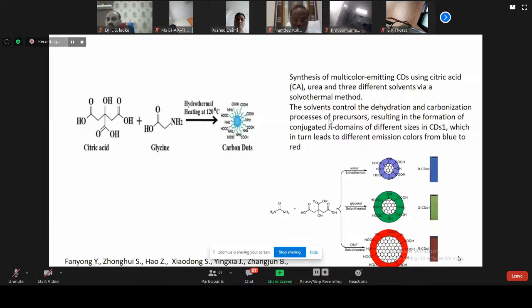Okay? So on the other side, we'll see a typical example of a multicolor emitting carbon nanodot using citric acid, urea, and 3 different solvents. When I do my synthesis in different solvents, I'm going to have a particular color being emitted. When you look at the reaction, urea and citric acid in the presence of water, under solvothermal. Okay, we are using solvothermal in this case. When the condition is underwater, it is hydrothermal. But when it is another solvent, like you can see in the case where dimethyl formamide and glycerol are used, you call such conditions solvothermal. But the first one that is underwater is a hydrothermal process.